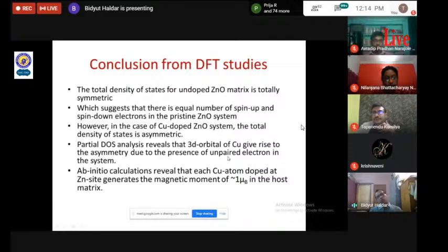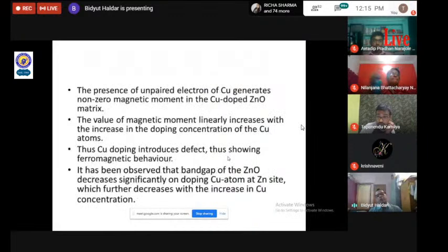Ab initio calculation reveals that each copper atom doped at a zinc site generates a magnetic moment of about 1 Bohr magneton in the host matrix. The presence of the unpaired electron of copper generates a non-zero magnetic moment in the copper doped zinc oxide matrix. The value of the magnetic moment linearly increases with the increase in the doping concentration of copper atoms. Thus, copper doping induces defects, showing ferromagnetic behavior. It has been observed that the band gap of zinc oxide decreases significantly on doping copper atoms at the zinc site, which further decreases with the increase in copper concentration.